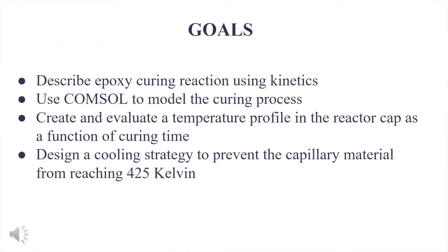The initial goal of this project was to develop an understanding of the kinetics of the epoxy curing reaction and to model this reaction in COMSOL with respect to the geometry of a capillary water filter. To appropriately evaluate the model, we had to create a temperature profile of the reactor as a function of the curing time. Our end goal was to design a strategy to prevent the glass capillary fibers from breaking under thermal stress while limiting changes made to the functionality of the water filter.